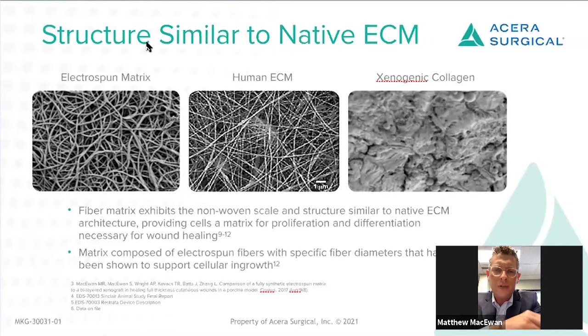And what's also really interesting is when you look at some of the other xenogenic or processed human allogenic materials that are out there, a lot of times all the chemical processing that you do to those tissues actually changes their ultrastructure to the point where it really stops looking like native ECM. So in a lot of ways, our synthetic materials are able to better mimic the structure of native human extracellular matrix. And that's really important because it allows cells to uniquely interact with these materials and essentially grow